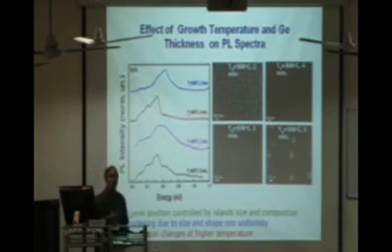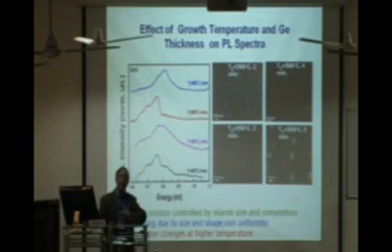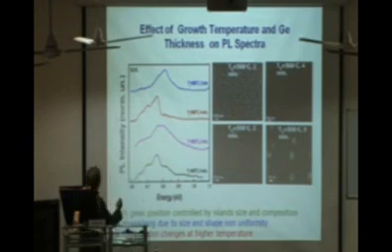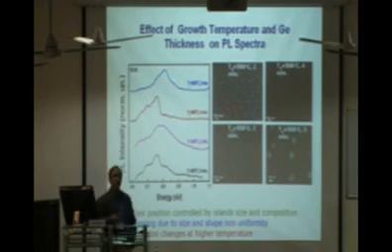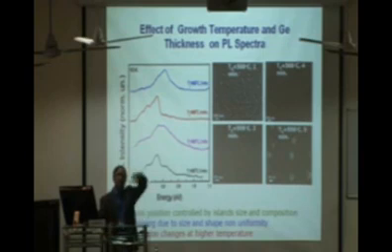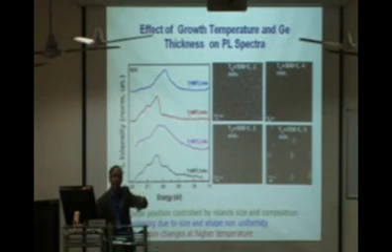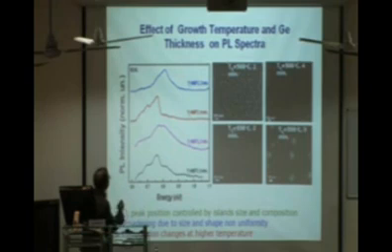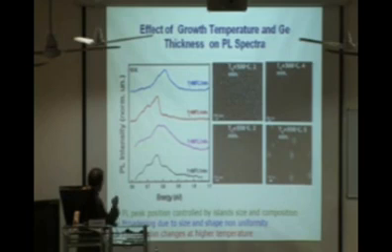Because of the formation of excitons, ultimately the excitons decay and recombine and give what is called photoluminescence. What we do is excite these quantum dots with lasers, and finally you see their recombination mechanism by an experiment called photoluminescence. This photoluminescence experiment is done for these germanium quantum dots. Normally the photoluminescence is taken at a low temperature like 10 Kelvin, and we can get very good emission.